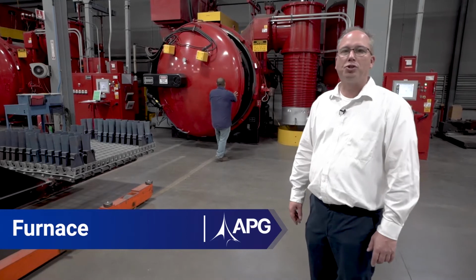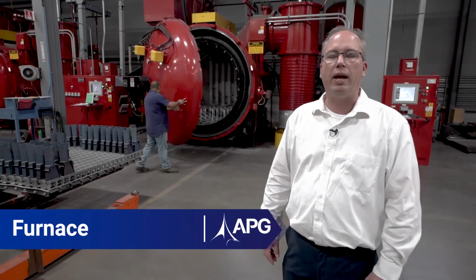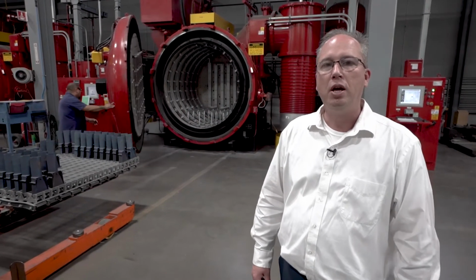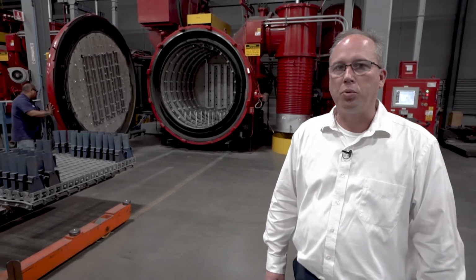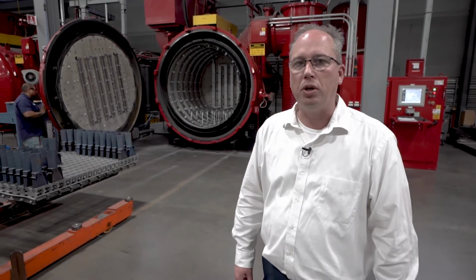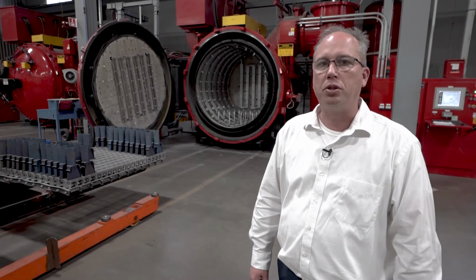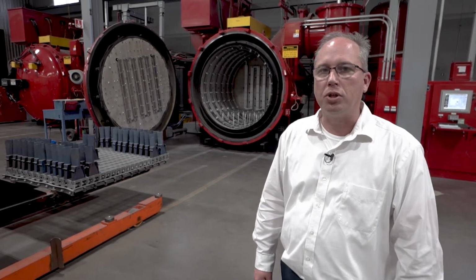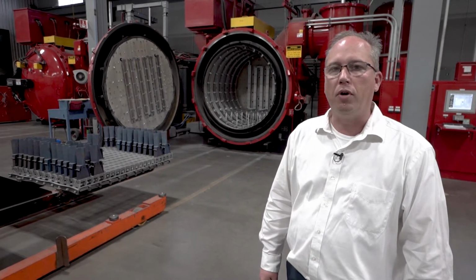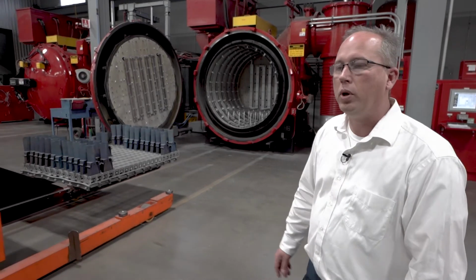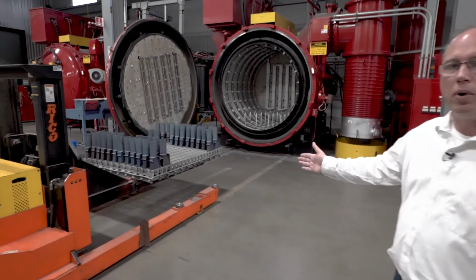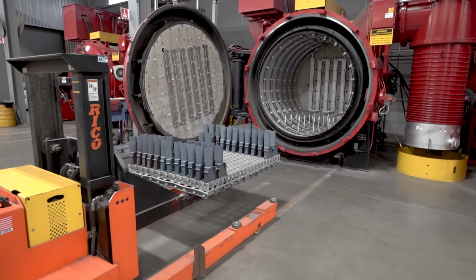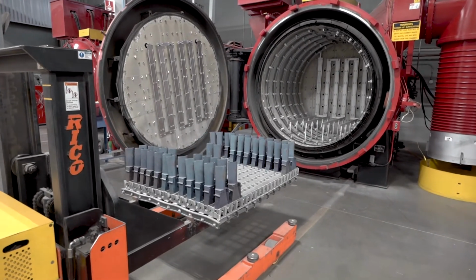Allied Power Group has two 48 by 78 by 48 hot zone vacuum heat treat furnaces. These are utilized for pre-weld, post-weld, coating diffusion and age heat treatments, and also for braze cycles. We perform a bi-weekly hydrogen clean and a quarterly survey of all of our furnaces. Also, we load our buckets vertically in the rack in order to heat treat so that we avoid any distortion during the heat treat cycle.